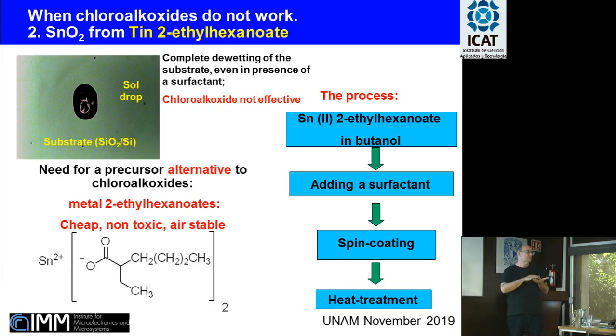There was no deposition. The substrate was completely repelling the solution due to the chemical composition or the surface tension of the solution. It was impossible to have a deposition. It was a real problem since tin dioxide is the most typical oxide that is used in sensing devices. So just for this material, it was not possible to get uniform thin films. It was impossible to get a film. There was nothing on the substrate.